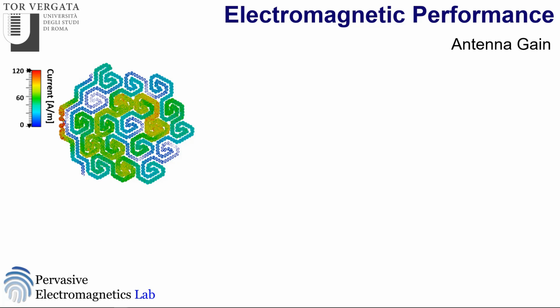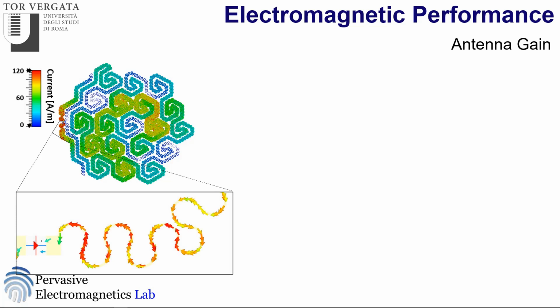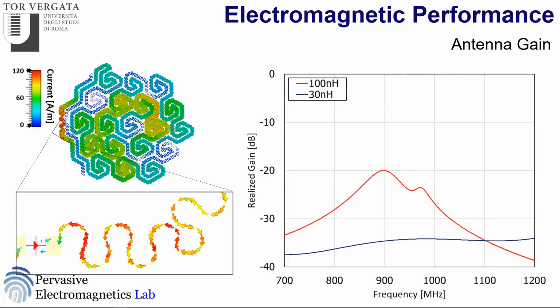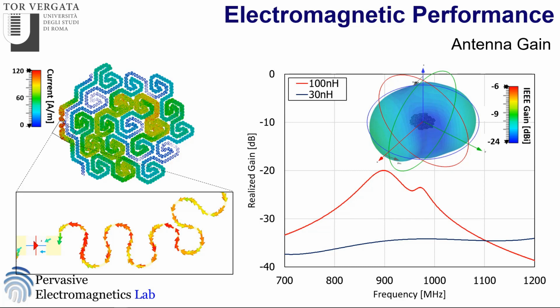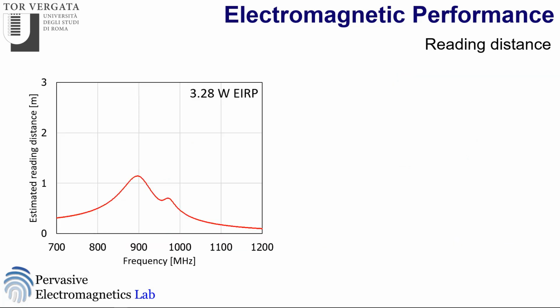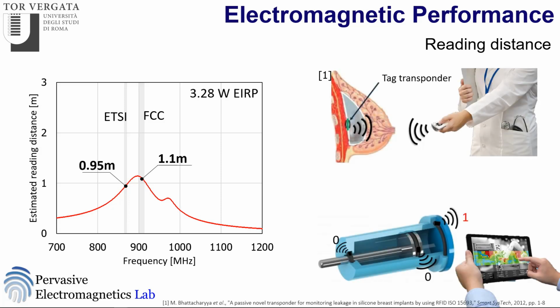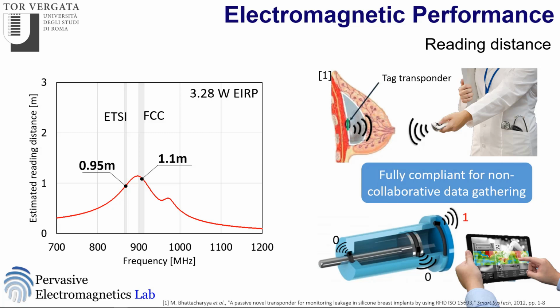The current is spread all over the structure due to the massive presence of metal. Moreover, the presence of a serpentine shape generates areas where the current is in phase opposition. This behavior affects the realized gain of the antenna. Anyway, the presence of the tuning inductors allows us to tune the antenna and maximize its performance in the RFID band. Here is reported the estimated reading distance. For the whole RFID band, American or European, we have an estimated reading distance of around 1 meter. This is fully compliant, for example, with a non-collaborative scenario for enabling a predictive maintenance service.